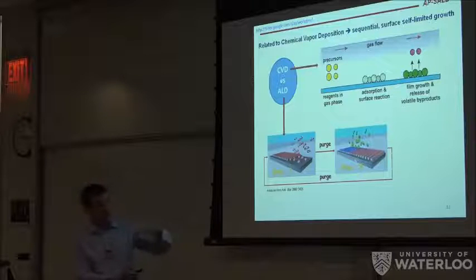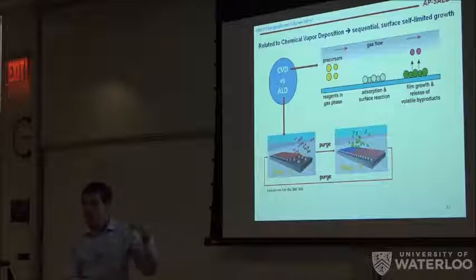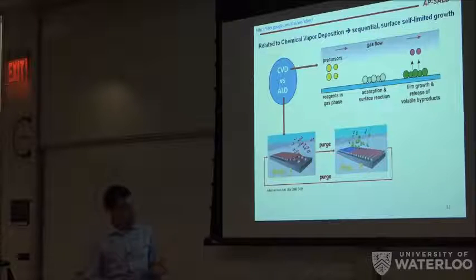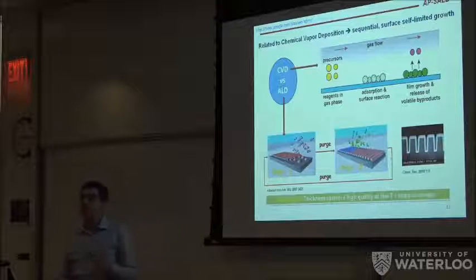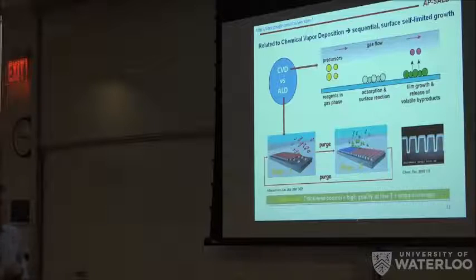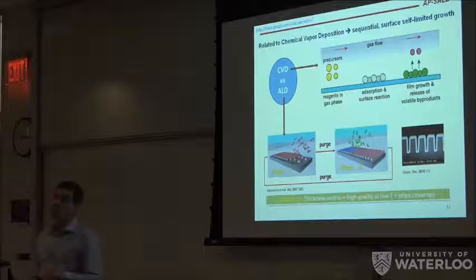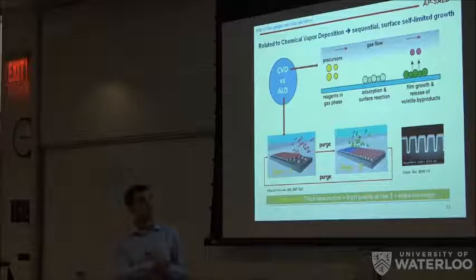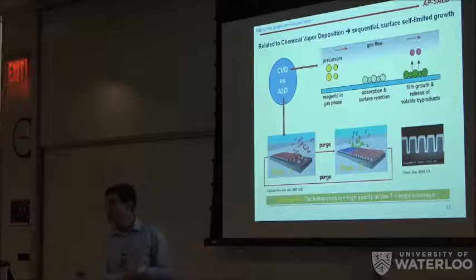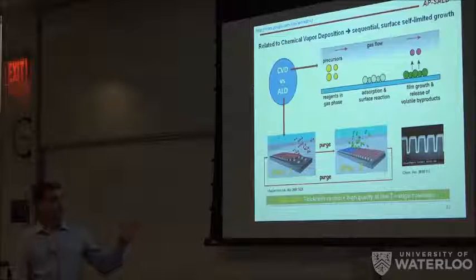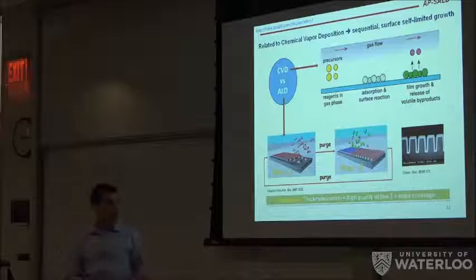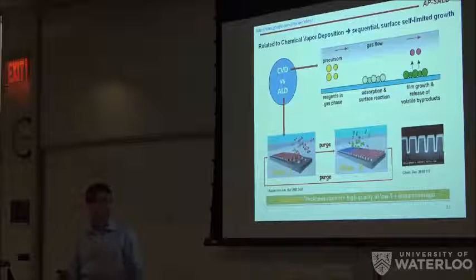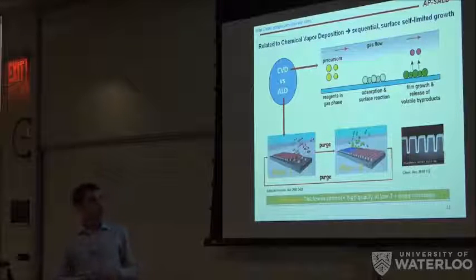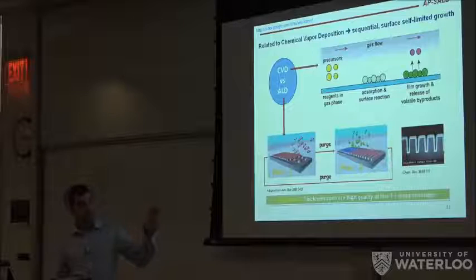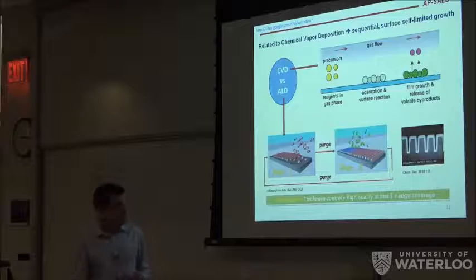And again, you wait for it to react completely, and any excess is purged. By doing the reaction in this way, you get unique properties. The first one is that the thickness is very precisely controlled, because it only depends on the number of times you repeat this cycle. You get growth per cycle, which is a particular one for each reaction and reactor, but once you know it, you can repeat it as many times as you need to get a particular thickness.